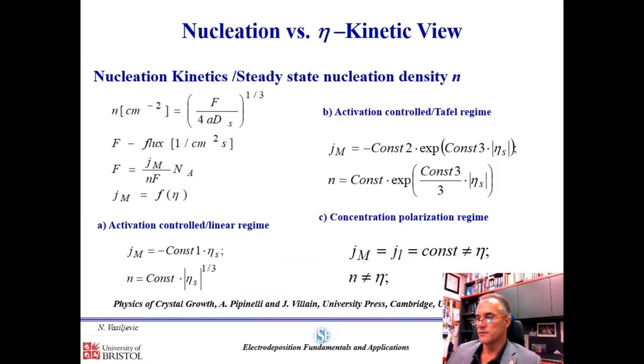Before I explain a few tricks for how we can do this, I would like to point out a few relations which are of interest for us. Looking at the nucleation density, which is a function of flux, and flux is a function of the current density, we can say that for the activation control regime, or for small overpotentials, which is typically the linear approximation of the Butler-Volmer equation, nucleation density is a third root of the overpotential function.